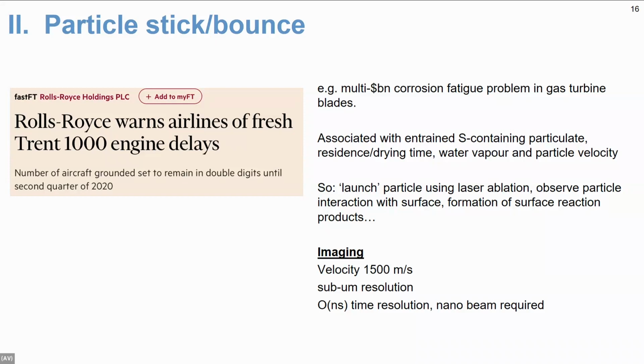There's a change in the way the ducts work. And so the sulfate particles that you have, imagine flying over Saudi Arabia, lots of talcum powder type stuff, then you're delivering that wetter, not fully dried out. And so your particles can stick rather than bounce effectively. And that's very hypothesis driven, because you can't then observe it afterwards. They all fall off, but it suddenly corrodes.